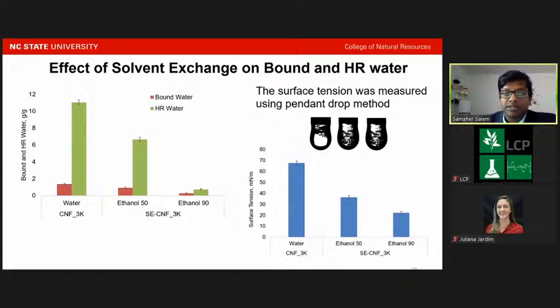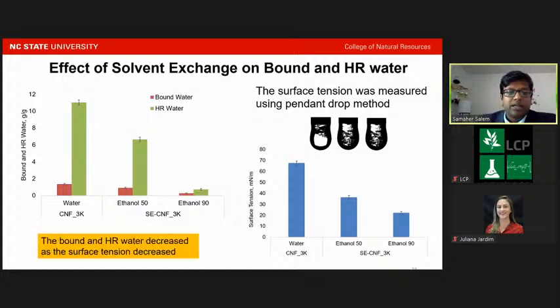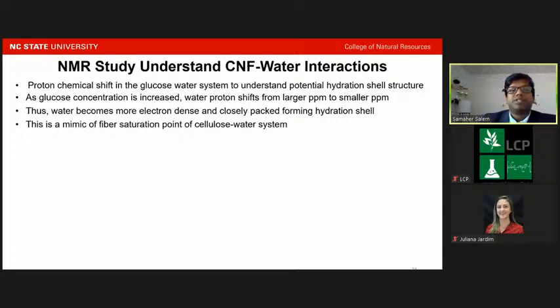And this decrease in the surface tension facilitated the movement of the acetyl group towards the cellulose surface and resulted in higher substitution, i.e. higher reactivity. We further studied this interaction using NMR. We measured the proton chemical shift in the glucose-water system to understand the potential hydration shell structure.